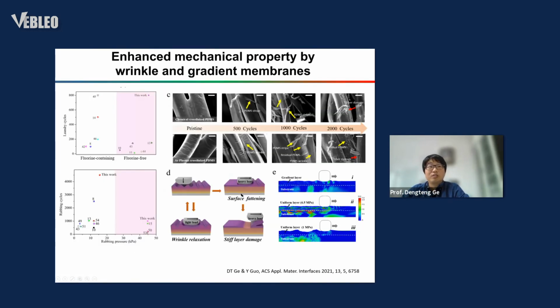We also test the robustness of the fabric. We found the fabric can bear very high laundering cycles and rubbing cycles. The results were almost the best among fluorine-free coatings. This reason could be attributed to two parts.